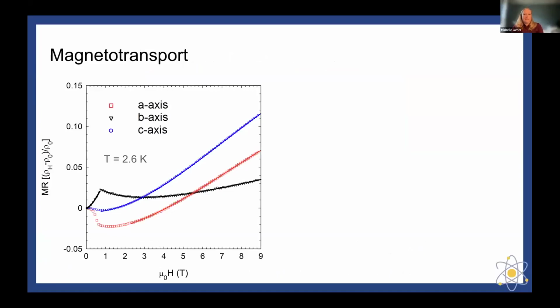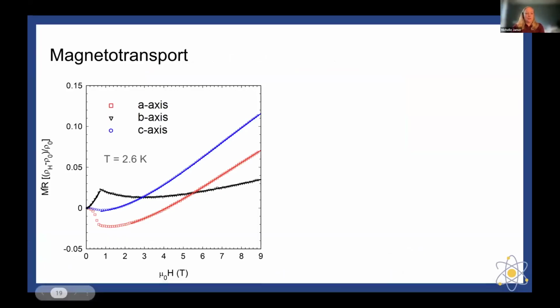So we took a look at the magnetotransport in order to try to figure out why the spins behave a certain way along different axes. We took a look at the magnetotransport where you apply magnetic field, you compare it to the initial resistance, and then you divide out the initial resistance at 0 field. So everything should be normalized at 0 Tesla to be 0. So this is a little normalization procedure.